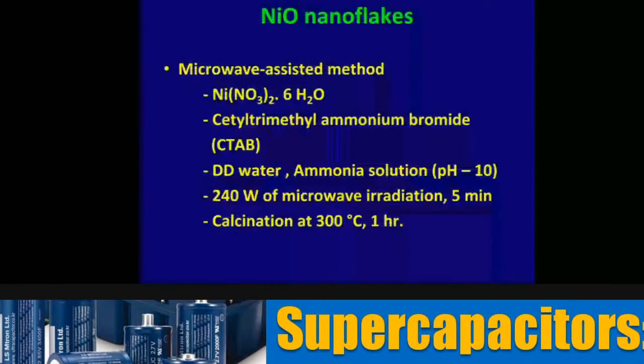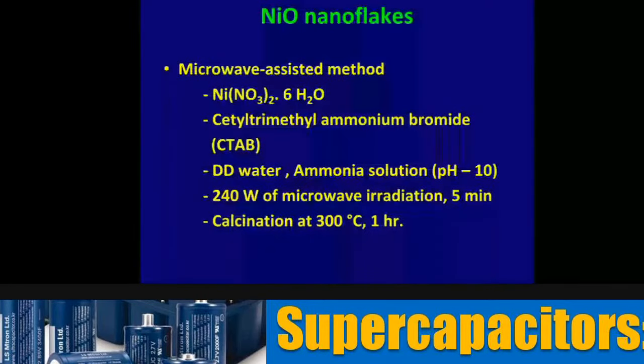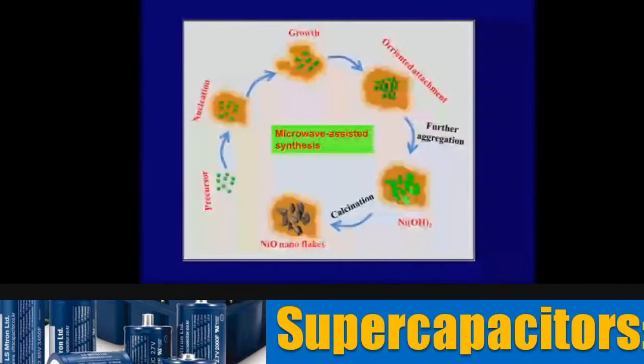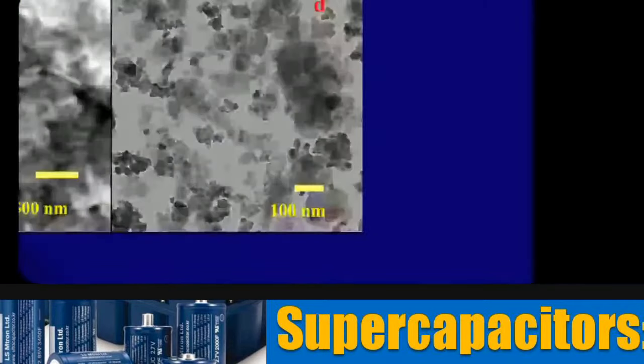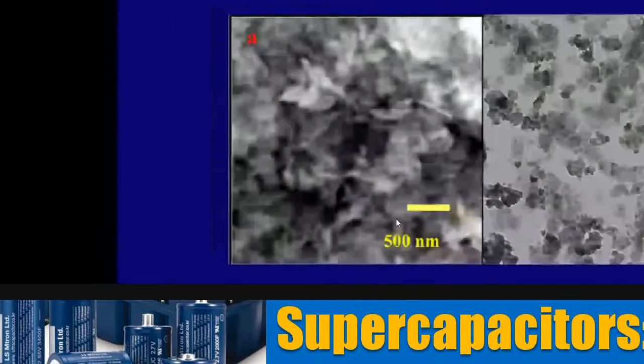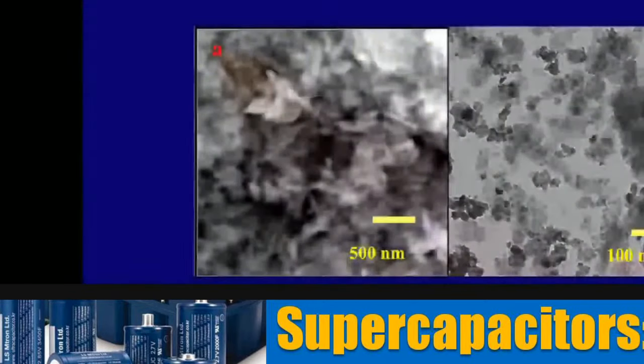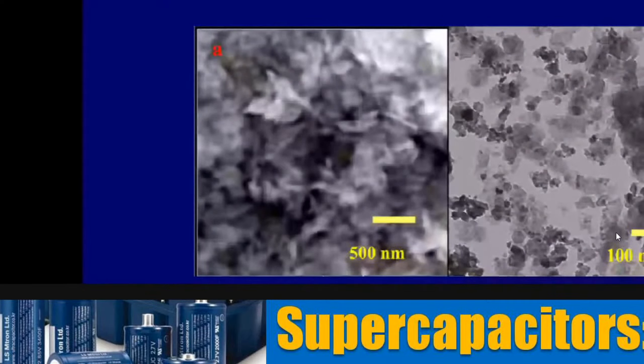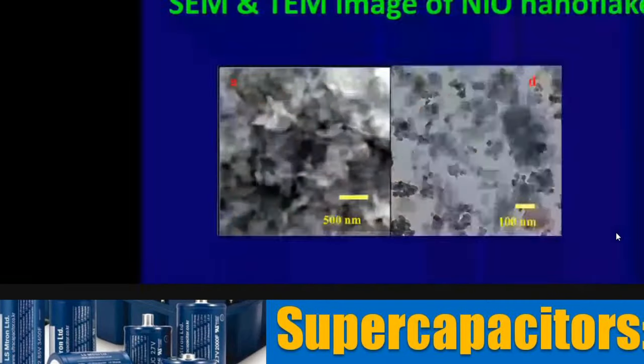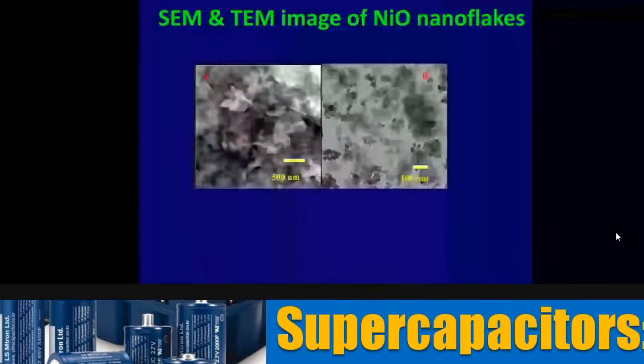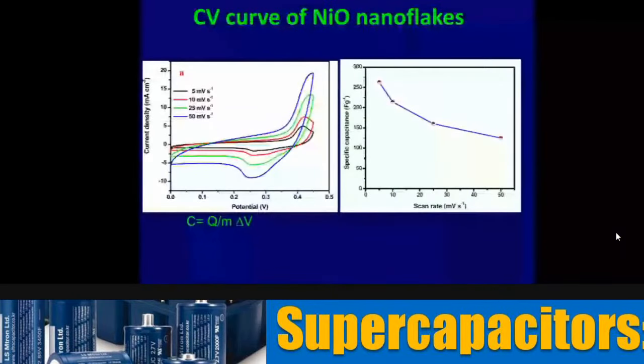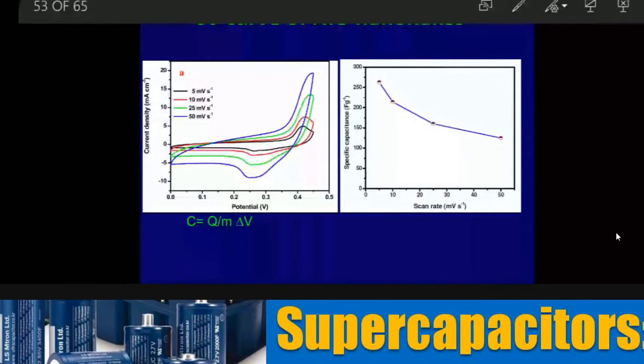We have used a microwave assisted method. Again, the precursor is nickel nitrate. We have used CTAB as the capping agent. And you see that the results are very good. You can see the flaky structure through the SEM picture, and you can see that the particles are almost uniform in the TEM image that you see on the right hand side. Again, you see that there is a retardation when you go at a fast rate.